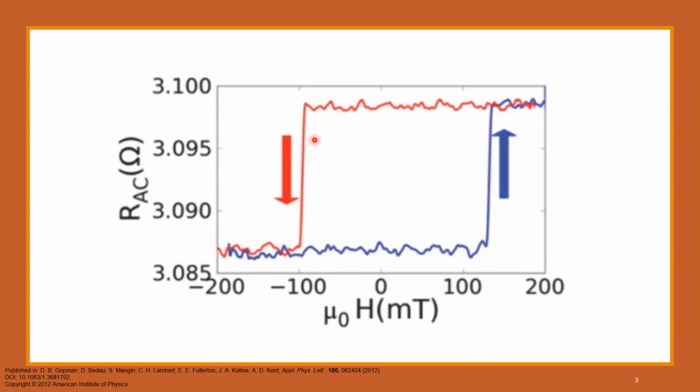The physical explanation behind it is that the spins of electrons in the current that passes through the polarizer will be aligned with the magnetization direction of the polarizer. If the magnetization direction of the layer is in parallel alignment with the polarizer, the current will pass through it more easily than if the magnetization of the layer is in anti-parallel alignment with the polarizer. The GMR effect explains why there is a change in electrical resistance, but someone can ask why there is a step change rather than a gradual change.